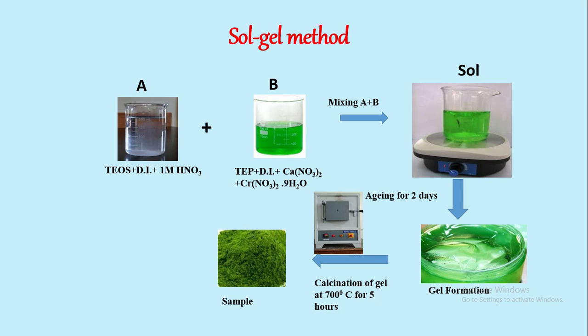Synthesis of biomaterial: we synthesize biomaterial with the sol-gel technique, which is the best technique. We take TEOS as precursor of SiO2, distilled water, 1 molar HNO3 acts as catalyst or gelifying agent, TEP as precursor of P2O5, calcium nitrate as precursor of CaO, and chromium nitrate nonahydrate as precursor of chromium oxide.